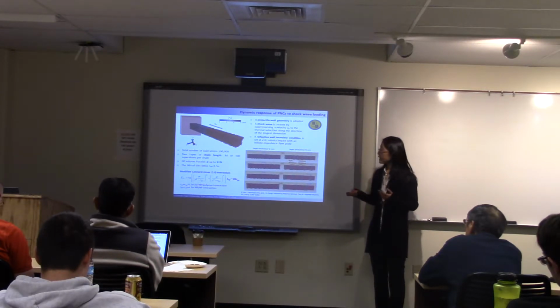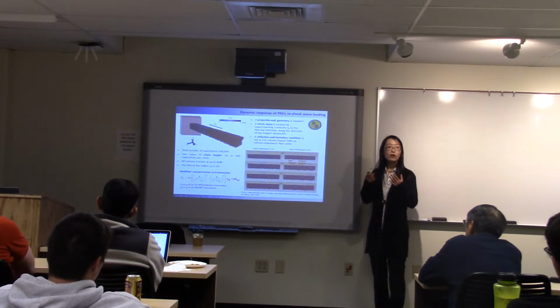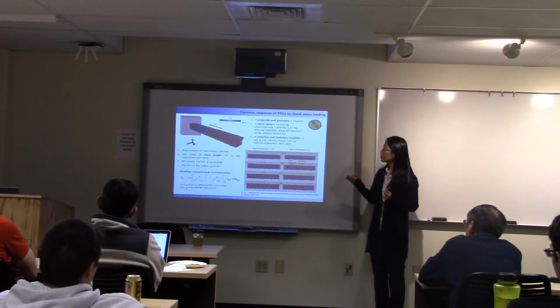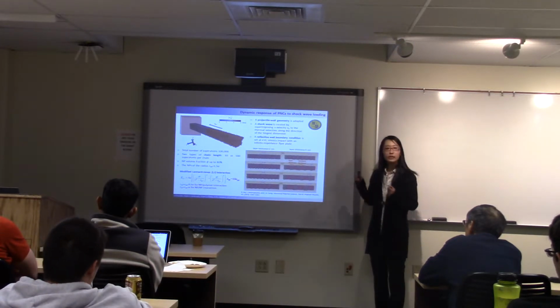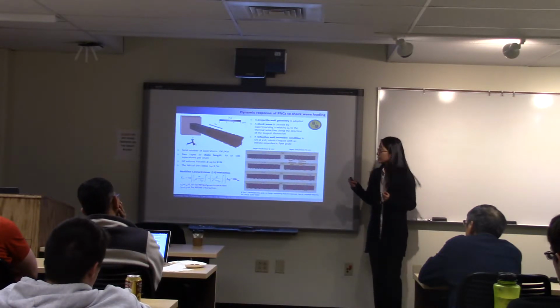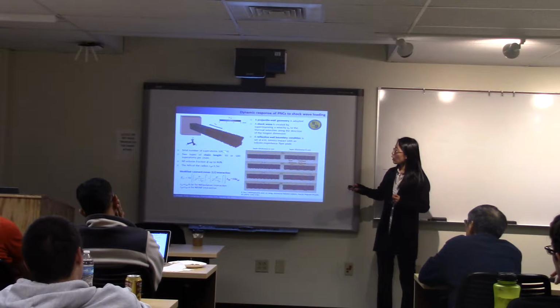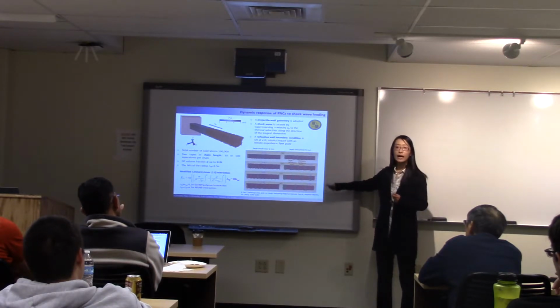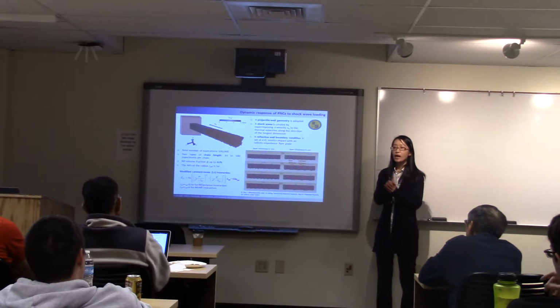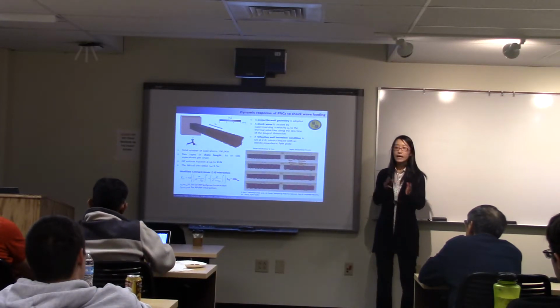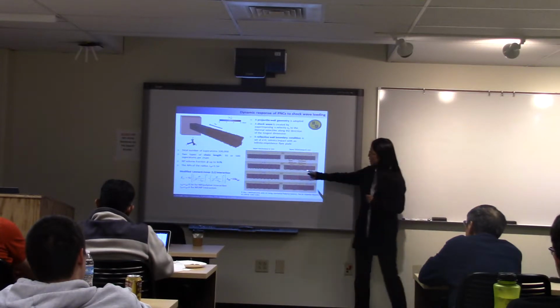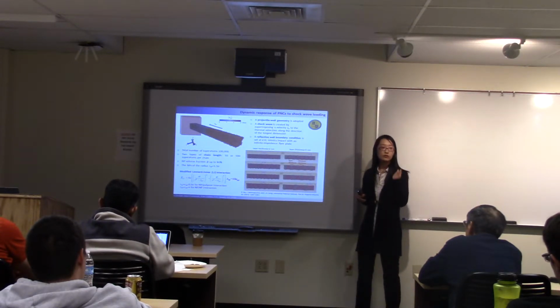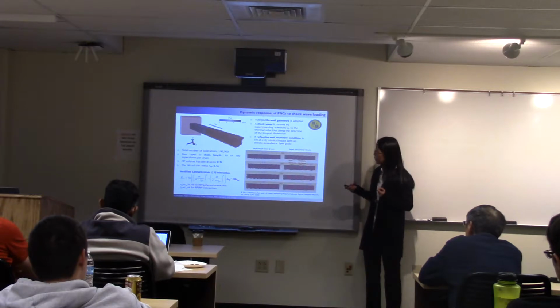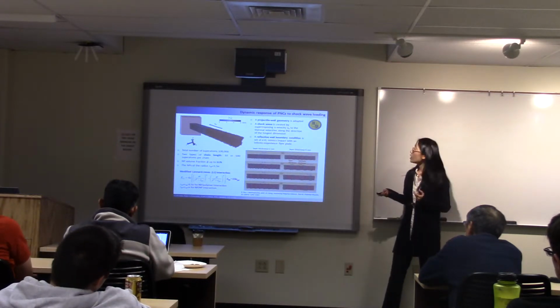Because from the previous studies, we find we need a strong nanoparticle-polymer interaction strength to reinforce the PNCs, here we choose a pretty strong nanoparticle-polymer interaction strength. Besides this uniform nanoparticle loading, we also design some microstructures by alternately aligning the nanoparticle-containing part and the nanoparticle-free part. The nanoparticle-containing part can be regarded as the hard region, and the nanoparticle-free part can be regarded as the soft region. So in total, we investigate 8 kinds of microstructure.